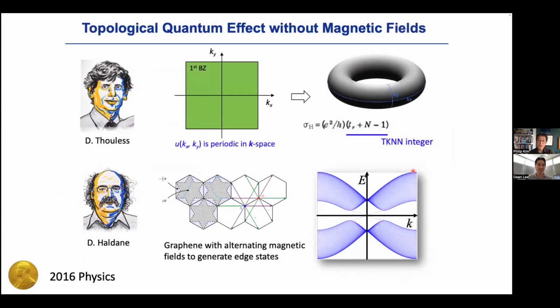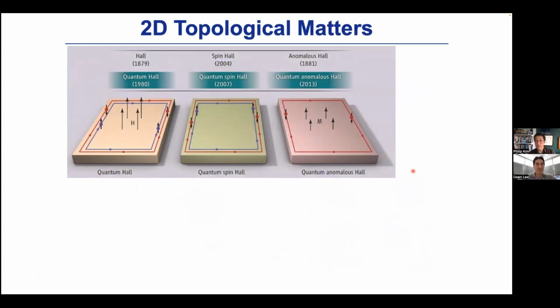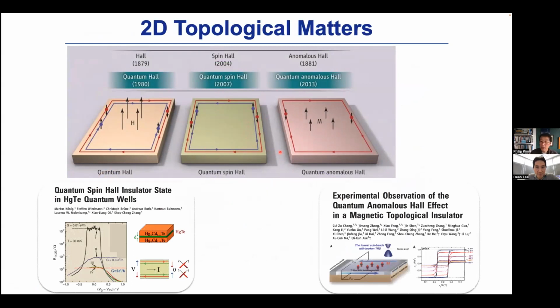Turns out, based on this, there are several important contributions from two theorists, David Thouless and Duncan Haldane. They extended this idea further and showed that you can build this topology into materials in such a way that, unlike graphene or a two-dimensional electron system, you don't necessarily need a magnetic field to see it. Following those seminal proposals, in the past 15 years or so, scientists found materials that can build up this topological edge state, which I will call the information highway, without a magnetic field. Materials have now been developed that create those topological states without invoking a magnetic field, based on these topologies.